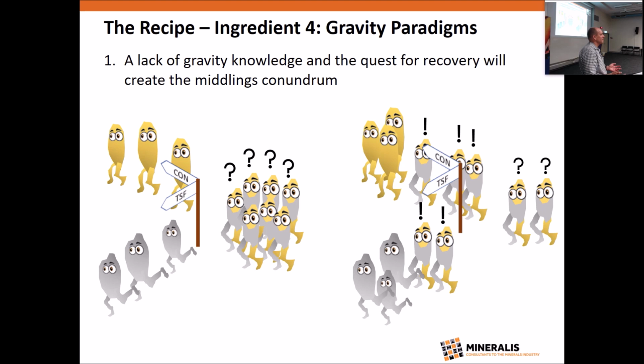And if you're running a gold gravity circuit like a lot of people are these days, in the presence of lots of competing minerals and sulphides in particular, if you've got intensive cyanide leaching in your toolbox, then making a low-grade middlings at a high recovery is fine. But if you can't use intensive cyanide leaching on your site, or for whatever reason, you're going to go back in time, and you're going to have to expend a lot of really hard work converting those middlings and those low-grade products into a smeltable concentrate and maintain a high recovery.